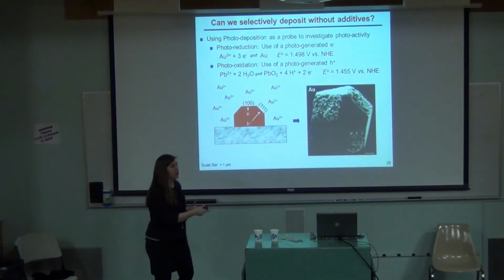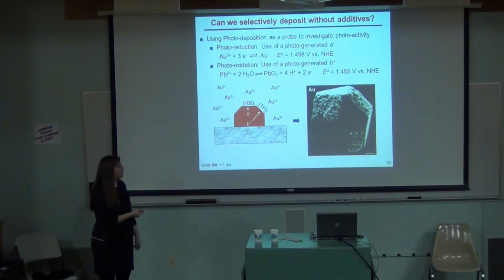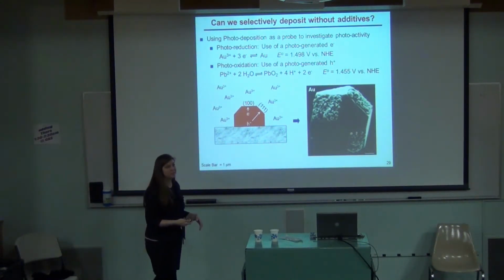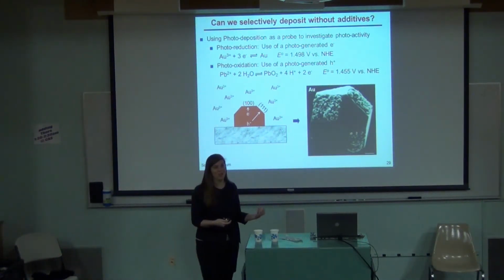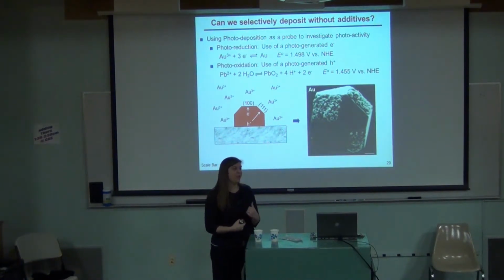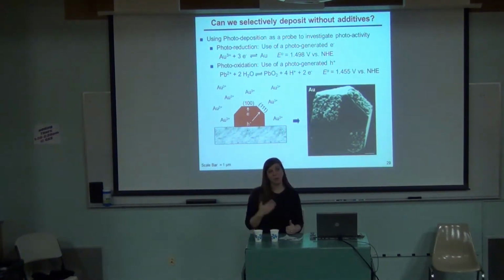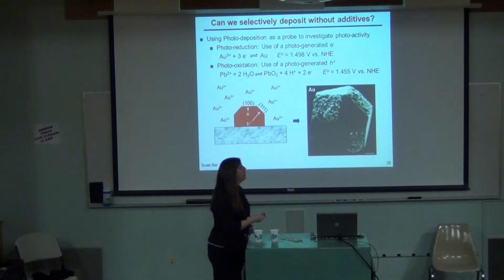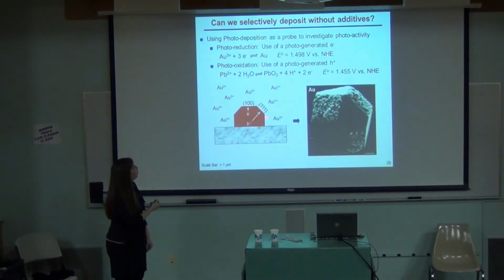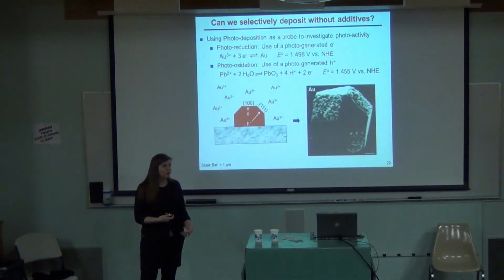So we thought that's where our gold would go. And in fact, we were encouraged at first that the gold did go there. And then I tried probably 50 other substances, and they all went there. So they all went on the 100 plane, and some of them should have been oxidized, so they should have gone on the 111 plane, because that's where the photooxidation would take place, where the holes are generated.